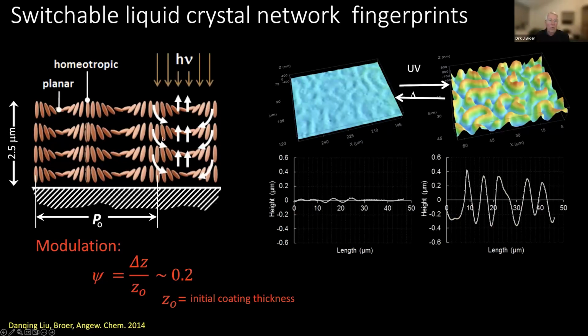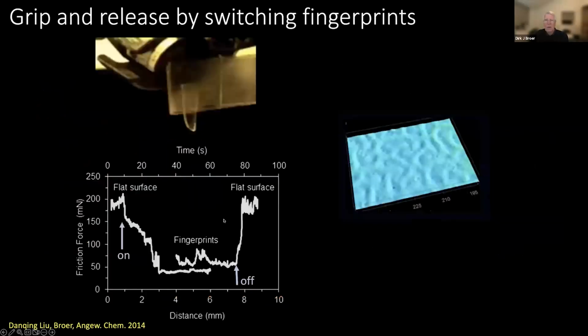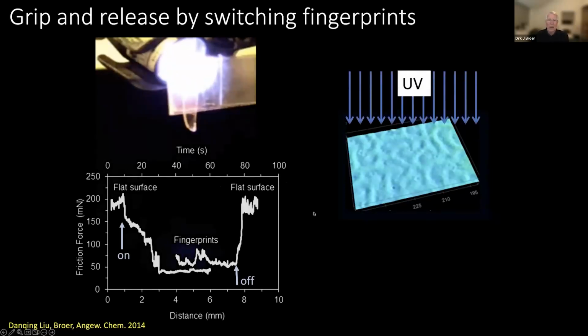And now, because of this double action, we basically get an expansion, which is about 20% of the initial film thickness. So in the case of a 5 micrometer thick film, now you can easily reach topographies which are in the order of 1 micrometer. And an early application might be if you use this system as a gripper.